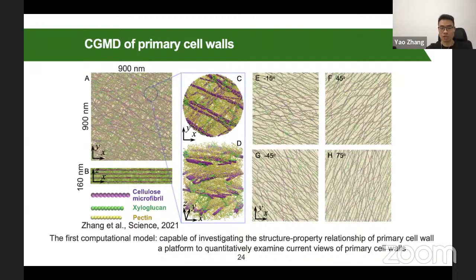Based on the microstructure we detect from the AFM, we got this coarse-grained model. In this model, the size is around 900 nanometer by 900 nanometer. We use a periodic boundary condition. And here you can see on this figure that we have 4 layers. Actually, in the real primary cell wall, it has around 200 layers. But here we can only simulate about 4 layers, but we use periodic boundary condition.